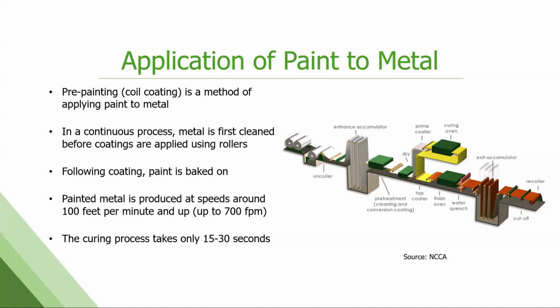So most of these lines run anywhere from 100 up to 700 feet per minute. And we can apply paint and cure it to a finished dry state in 15 to 30 seconds. This is a very generic schematic of what one of these paint lines or coil lines looks like here. They do vary a bit from manufacturer to manufacturer, but they all have the same pieces and parts.